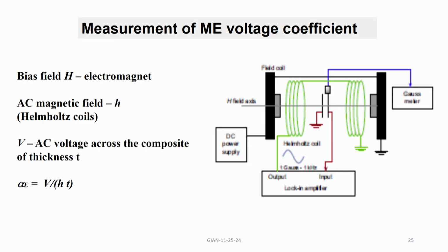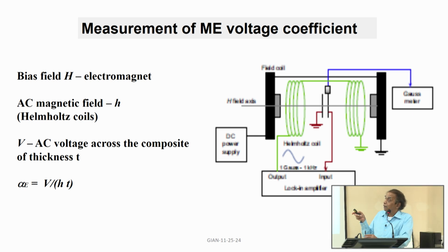So, this is something I want to show you this afternoon, I will show you the measurement system that we have in my lab, and it's very similar to what is shown here. To measure the voltage coefficient, you need a bias magnetic field. So we have an electromagnet to do that, and then the AC magnetic field is produced by a pair of Helmholtz coils. The sample is placed here so that the fields are all in this particular case. You can orient the sample parallel to this field, or you can turn it by 90 degrees to make it perpendicular to the field.